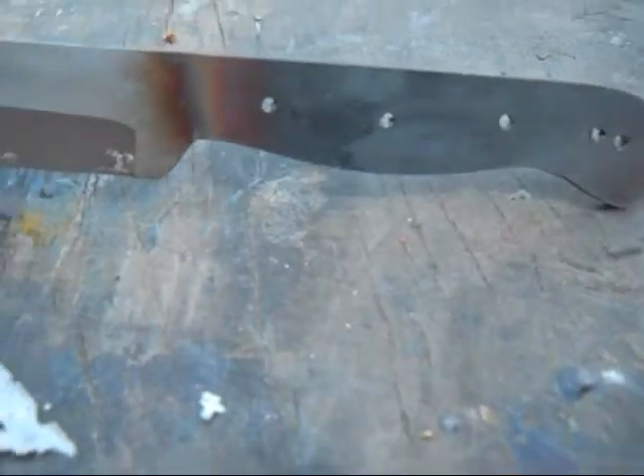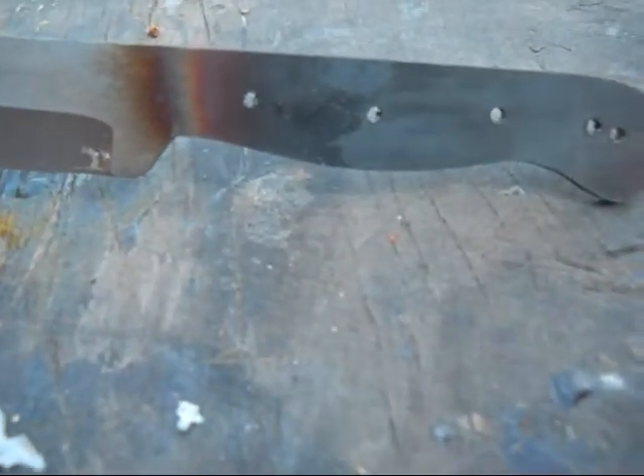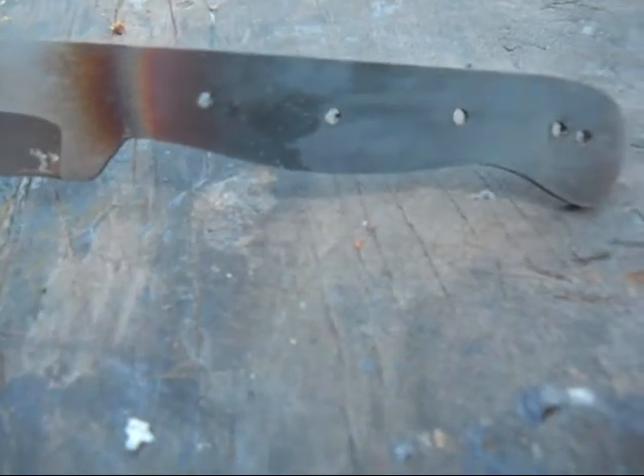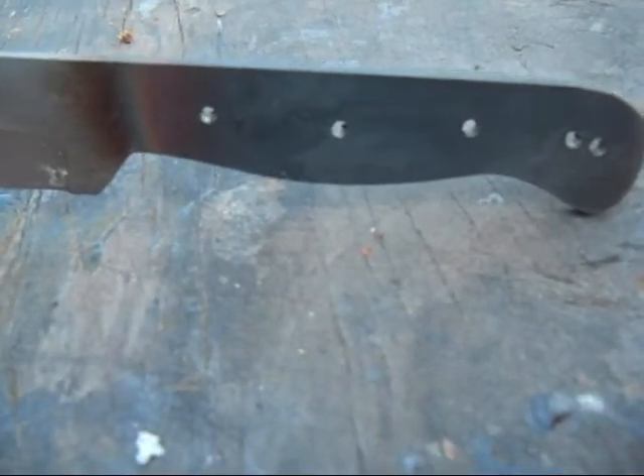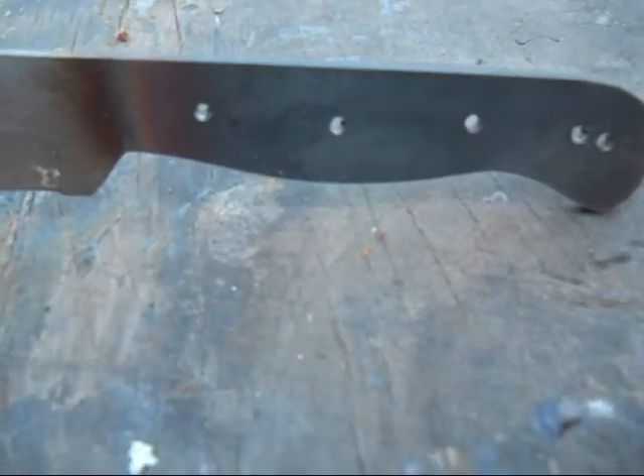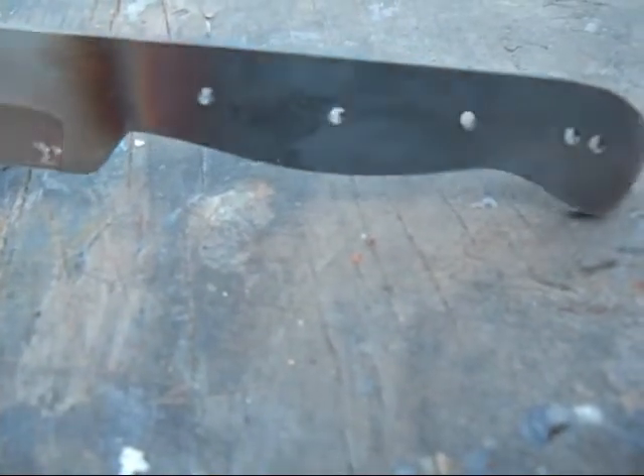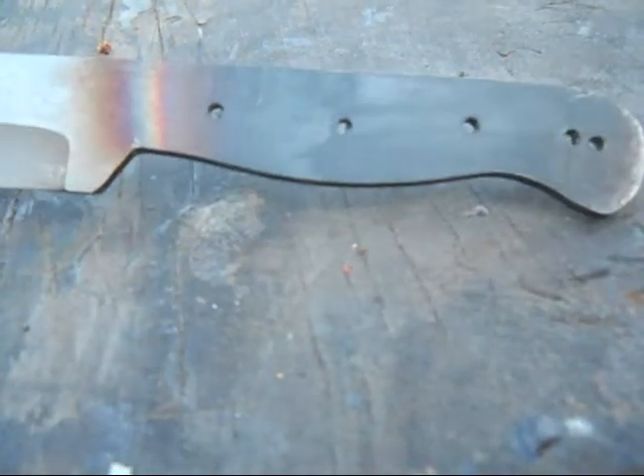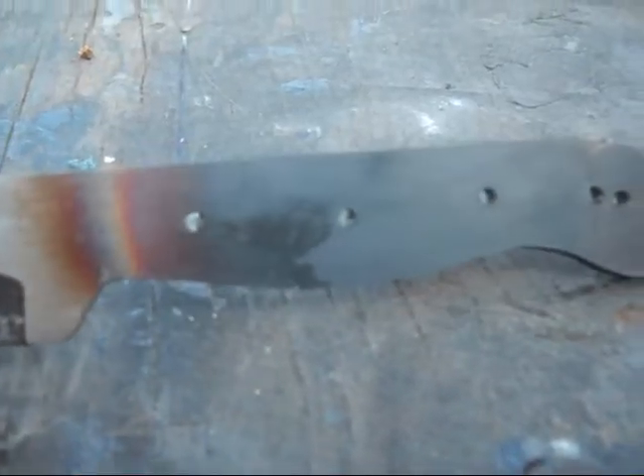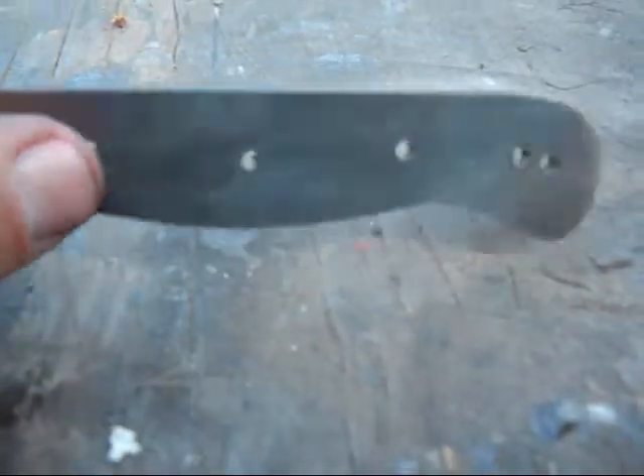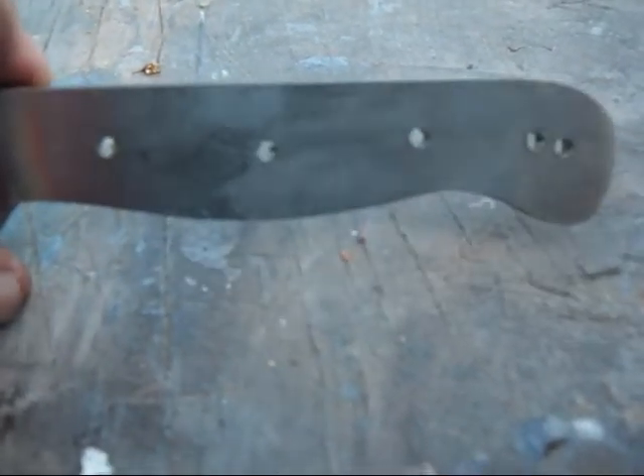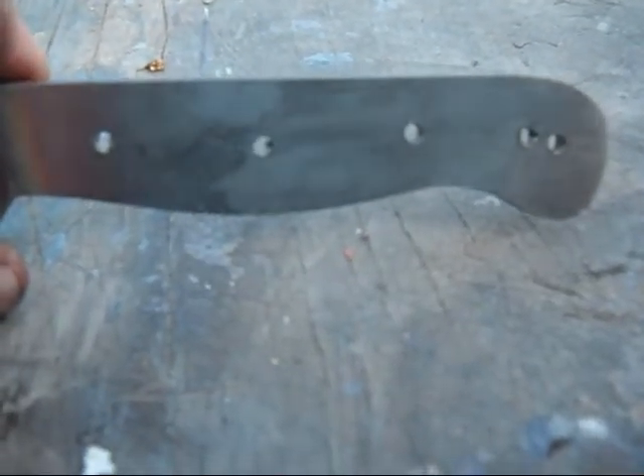As you can see, it gets the job done. I mean, it's not quite as good as annealed steel. It did soften it up some, so I guess technically that's annealing, but not like doing it in the oven, doing the whole blade, and doing it properly, letting it cool down slower. Possibly, if after heating a blade you put it in vermiculite or something to have it cool down slower than just air cooling like I did, it might work better. But this worked enough to get the job done.